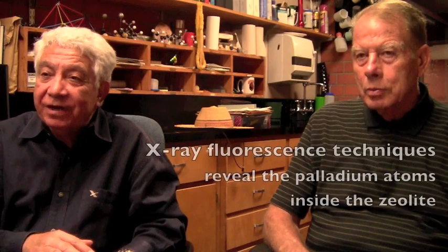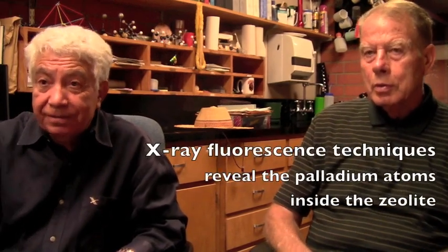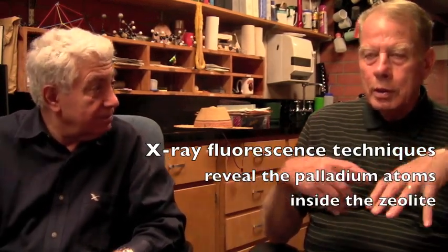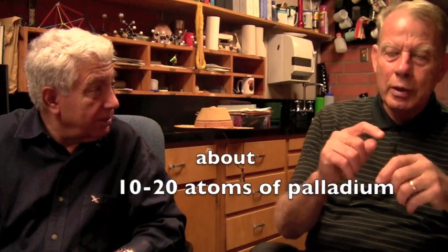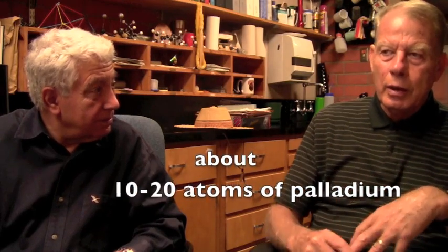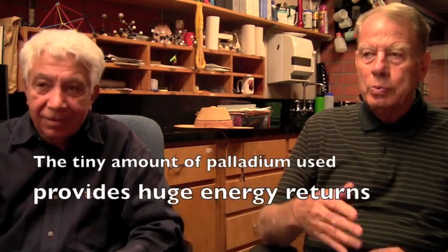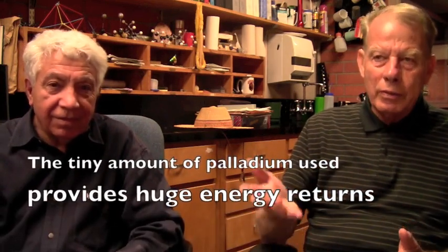With the X-ray fluorescence, we see a lot of palladium in there. But it's not a big clump of palladium, it's just very small, maybe 10 atoms or 20, we don't know. What's really surprising, he gets a measurable heating effect on a very small amount of palladium. So per gram of palladium, he's getting a very big effect.